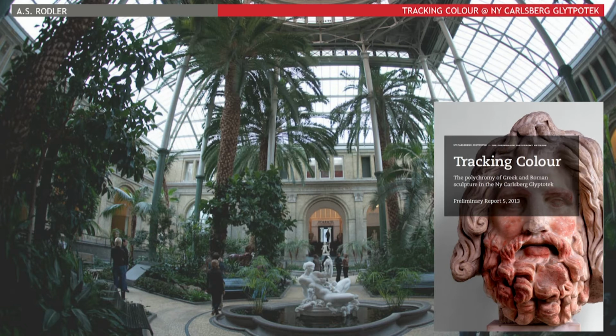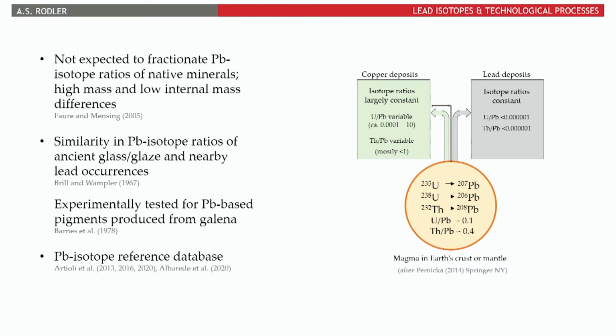And for pigment provenance analysis, I used the trace element composition and specifically the lead isotope composition of pigments. And this can show us when geological materials, such as copper minerals, were formed, geologically speaking. And because ore deposits have different ages and formation histories, we can use this to tell them apart. Now, when using lead isotopes for pigment provenance studies, we work with the understanding that technological processes are not expected to change the lead isotope composition between the raw material and the pigments. This has been tested for ancient glass and lead-based pigments, and we compare to large lead isotope databases to exclude the least likely source areas.